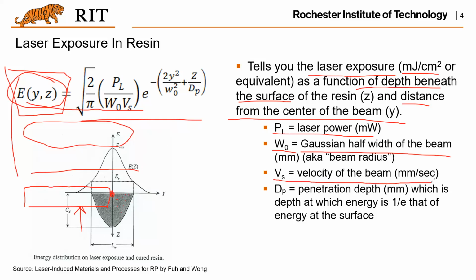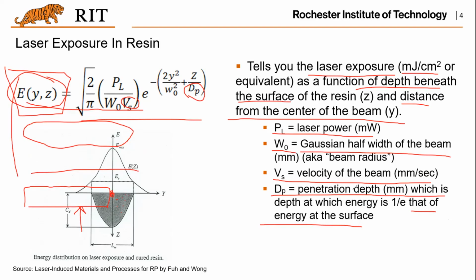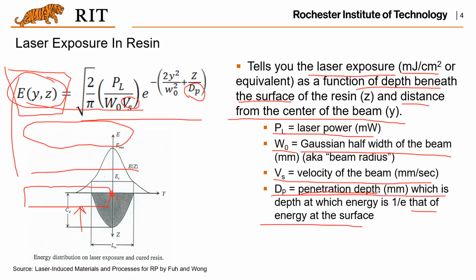And another parameter in this equation is the velocity of the beam, Vs. So you can see here, it is placed over here, and the penetration depth dp, which is put here. As I mentioned, dp is the depth at which the energy is 1/e of the energy at the surface. So basically, the energy becomes lower and lower with the distance increase from the surface. So if the energy becomes 1/e, that will be the penetration depth we use here. So basically, we need to use this equation to do some computation.